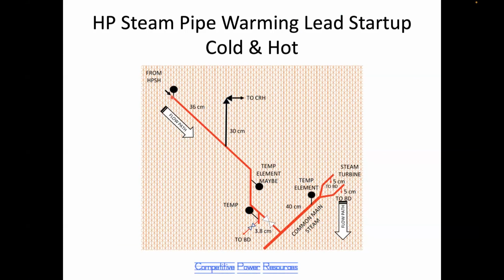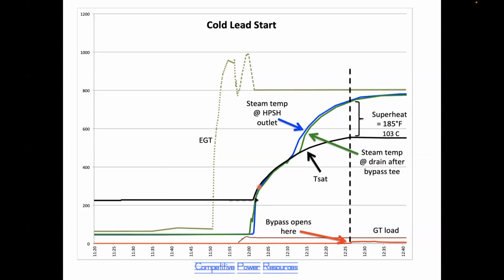The blue line is this temperature, and the green line is this temperature. So they both follow saturation temperature as that pipe is warming, but at some point here, they become superheated. The bypass opens here. By the time the bypass opens, there's 103 degrees superheat in the steam it's receiving. So there's no problem with this cold lead start. The first unit start cold, no problem at all.